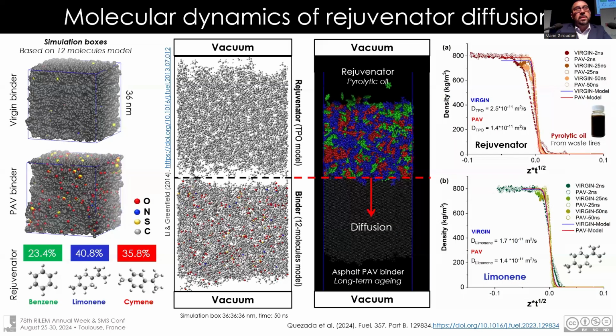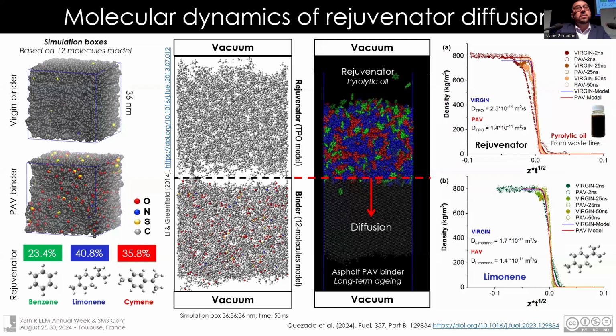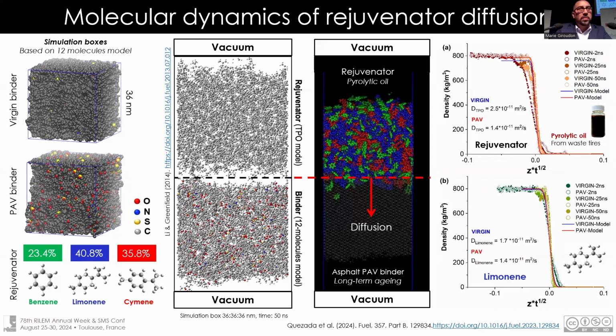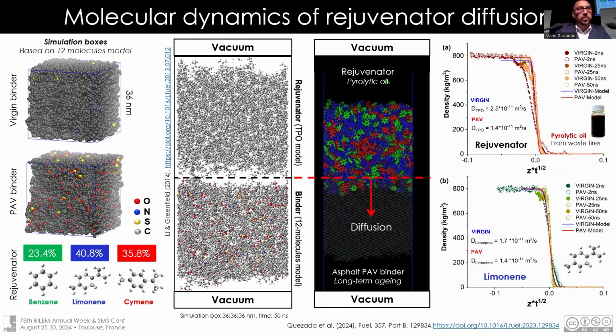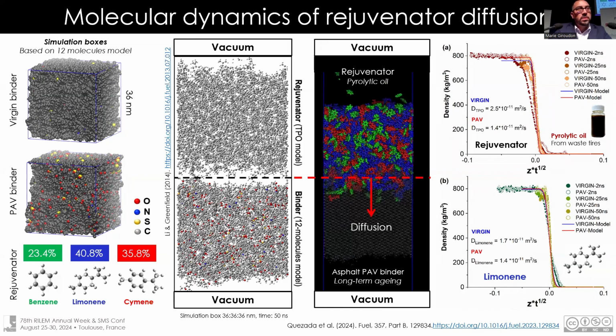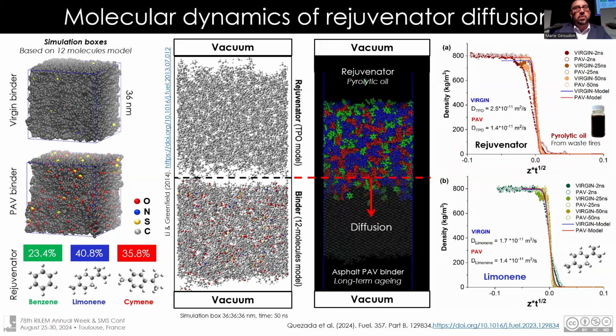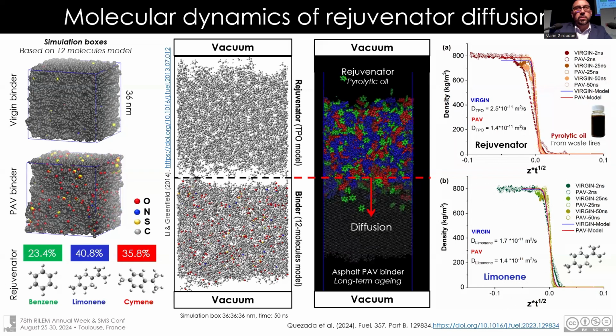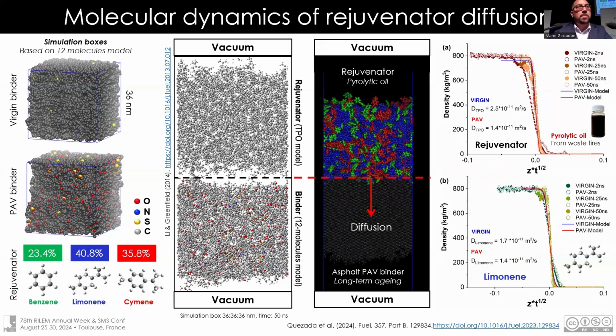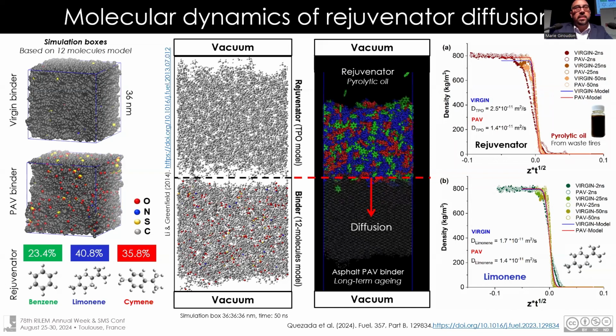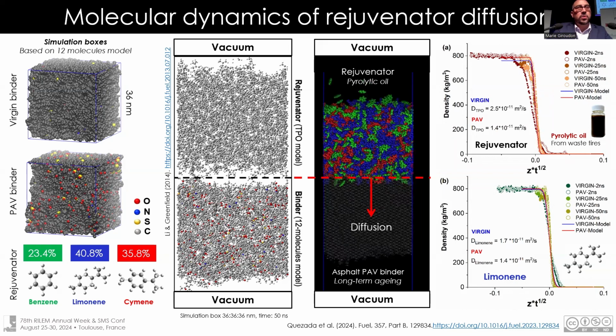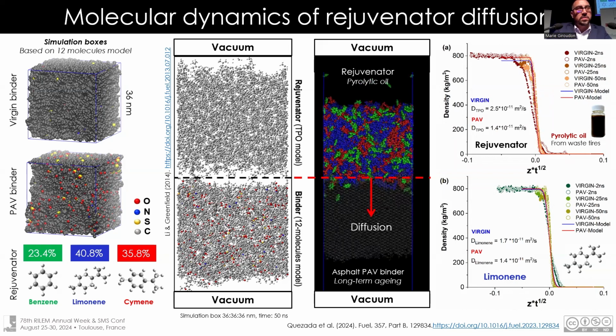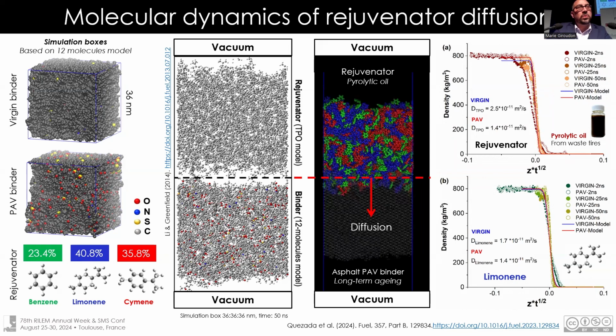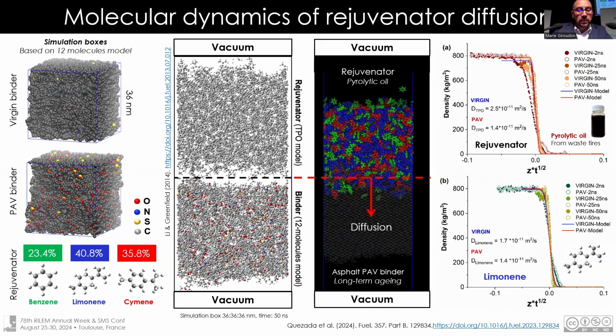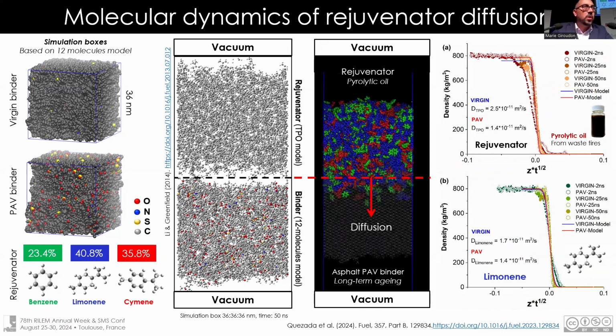At molecular level, it's possible to use molecular dynamics to evaluate an important process when you use rejuvenators. The name is diffusion. The diffusion is very, very important because if you can control the diffusion, you can increase the properties of the rejuvenator inside the materials. That is very difficult to evaluate under laboratory conditions using microscopy, for example. It's necessary to incorporate molecular dynamics approach in order to evaluate this phenomenon. And you calculate the diffusion coefficient, etc.